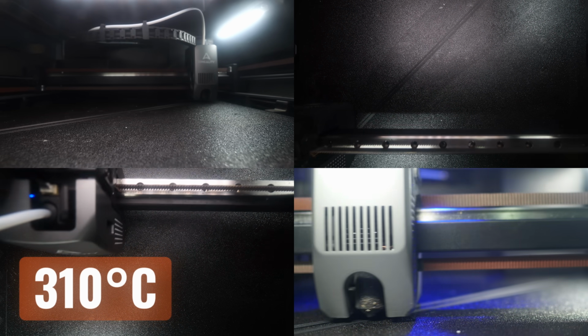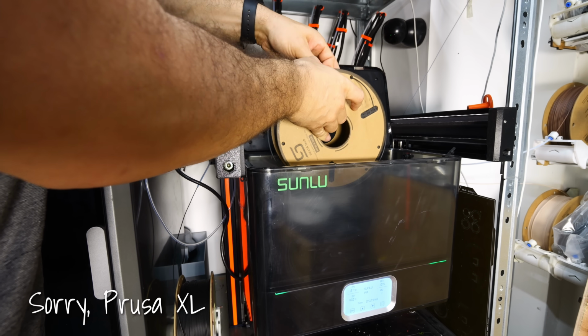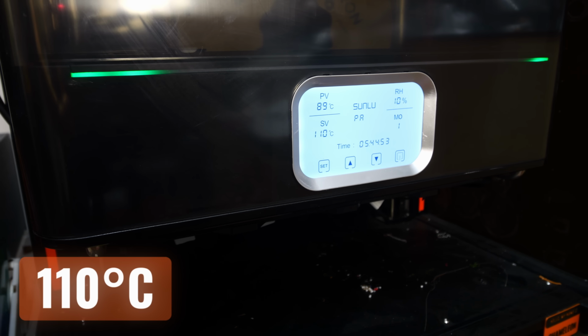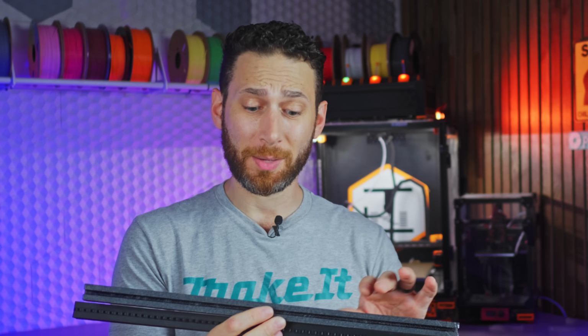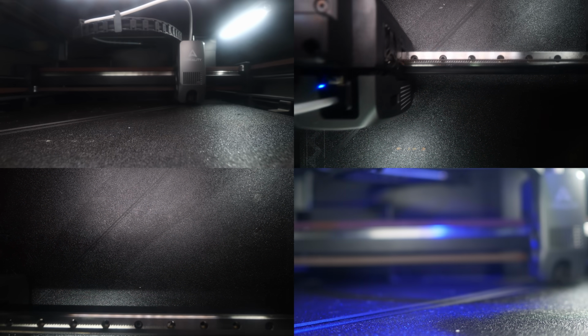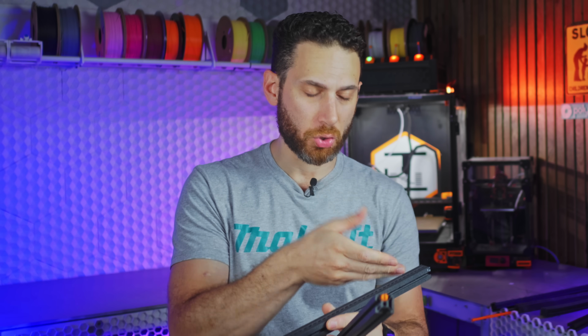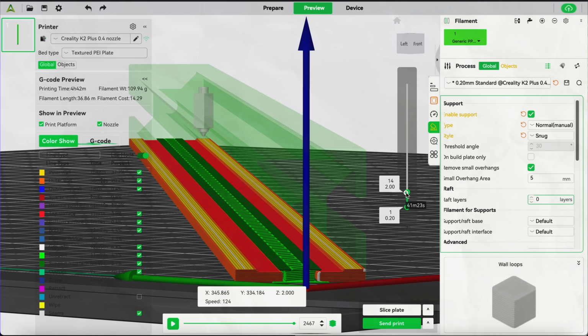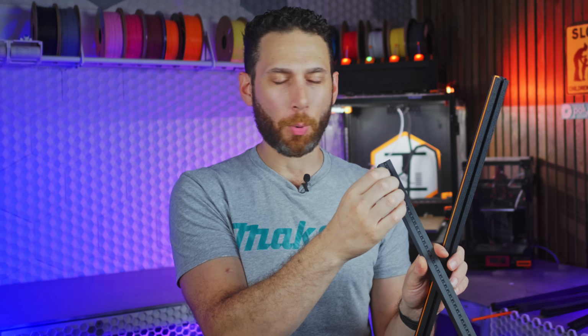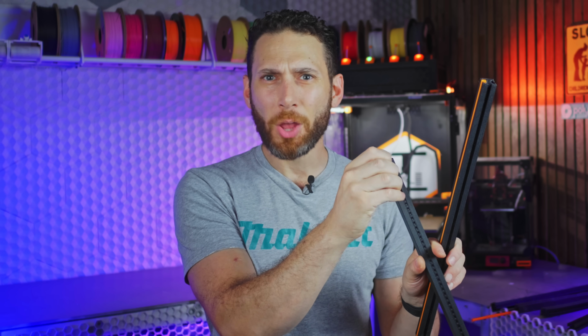Check it out. I printed these extrusions on the Creality K2 Plus at around 310 degrees Celsius directly from Sunlu's E2 filament dryer running at 110 degrees C. I also generously applied Magigoo's PA bed adhesion product, and I honestly expected some failures and tuning, but to my surprise, they printed absolutely perfectly the first time without a hitch. I also had been worried about supports and removability on such a strong material, but the profiles on the K2 honestly were actually really good, and support removal was, look at this, no problem.